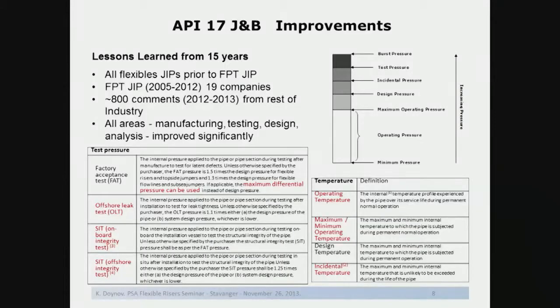We introduced a similar structure for the temperature as the one for the pressures, and this time make clear that the FAT test can actually be based on a differential pressure as opposed to design pressure in certain cases, and introduce definitions of an offshore leak test, structural integrity test on board of an installation vessel, or structural integrity test in situ, meaning for accidents that happen during installation you have to repair and then you can put the line back in action.